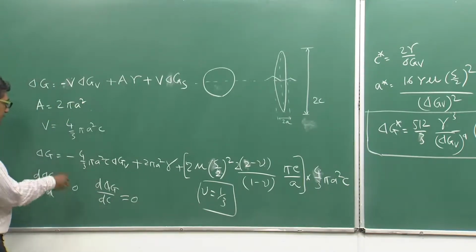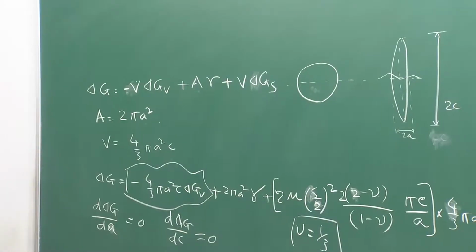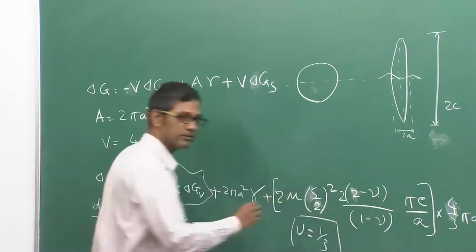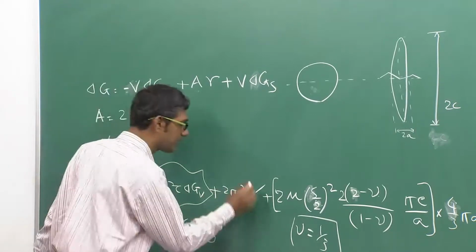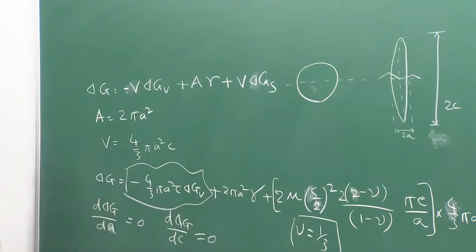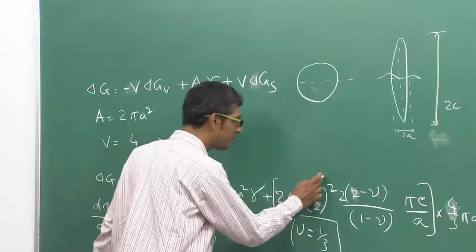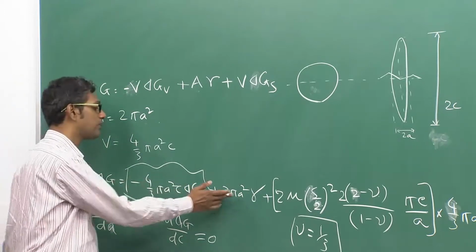But if this is my free energy available to me chemically because of quenching, this is used to create interface and to take care of strain. Now interface is fine, you are forming a new phase, interface will be there. But here the interface energy will not be very high, because there is a distinct crystallographic relationship between martensite and austenite. But the important thing which will be high here is the strain energy part, and this is substantially higher as compared to the surface energy part.